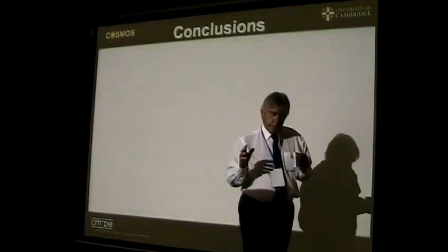Your last slide concluded that the laser is easy to control by the mechanical deformation and temperature. But I want to know, is it stable for the laser output? Yes, is the answer. Stable in terms of lifetime. That was why I showed you the mechanical, because the mechanical is easier and harder. It's easy in the sense that it's an elastomer, so it's mechanically rugged, but you get several lines because of the different domain size in the elastomeric network.